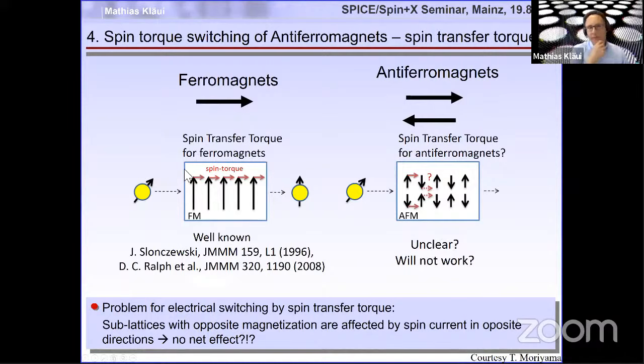So we see here that for ferromagnets, it is very well established that this can be done by spin torque. We inject a spin polarized charge current into the ferromagnet. The spin polarized charge current then exerts a torque on the spins and thereby switches the magnetization by a transfer of spin angular momentum. Now, for an antiferromagnet, this shouldn't work because you have spins which can interact with both sublattices. And this sublattice here would be rotating clockwise, whereas the next sublattice here should be rotating counterclockwise. And since we know that the antiferromagnetic coupling is extremely strong, we'll not be able to do that. So the question is, is there no net effect?